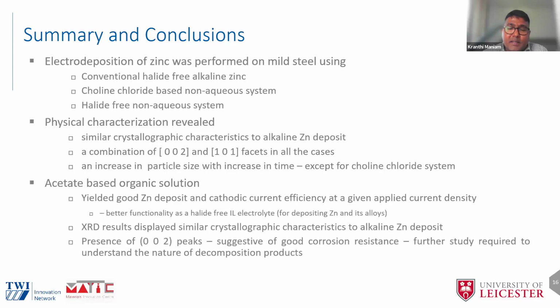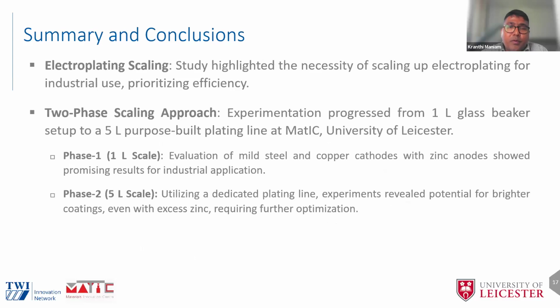And the most important thing is that we could get the 002 peaks, which suggests good corrosion resistance. And also we could do the electroplating scaling. So the study highlighted the necessity of scaling up, which was a part of the project, and I could do it in 2 phases. One is the 1 liter scale, and once I was successful with that, I could expand it to 5 liter scale. This showed the potential route towards commercialization, and I could demonstrate that it has the capability to achieve commercial scales.